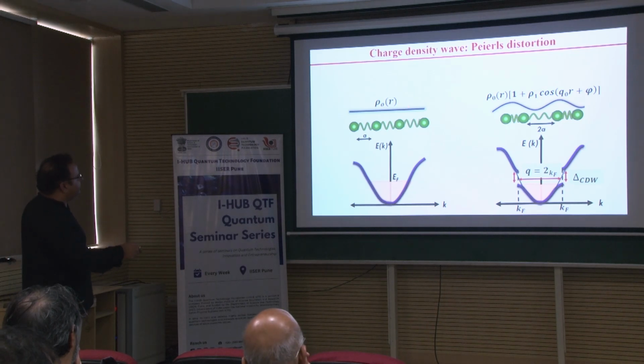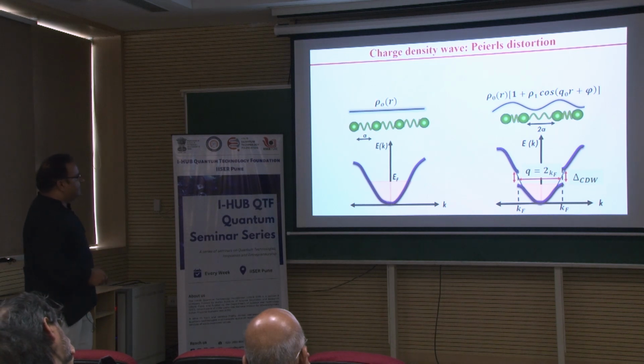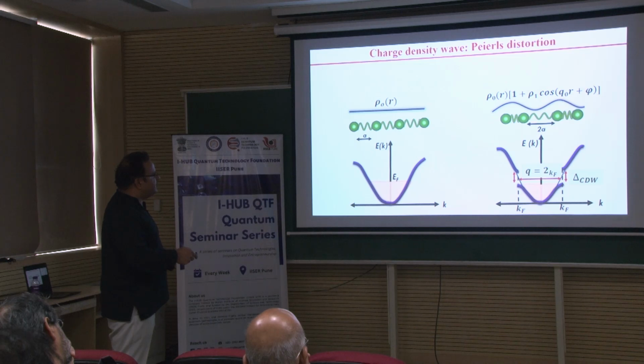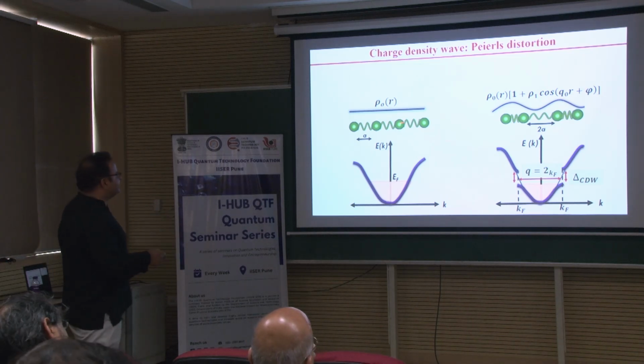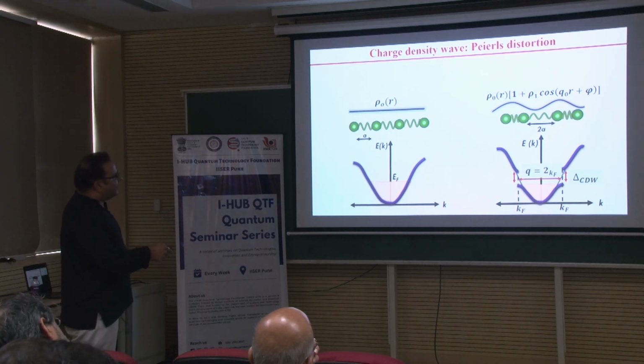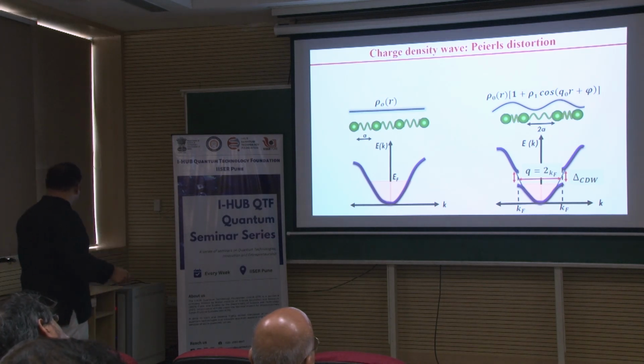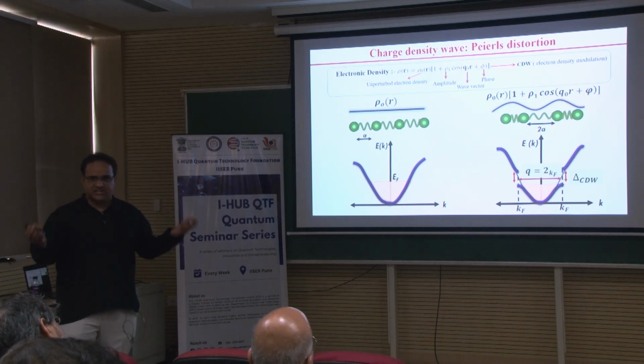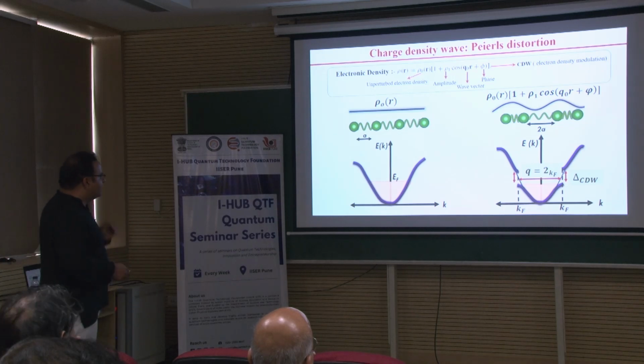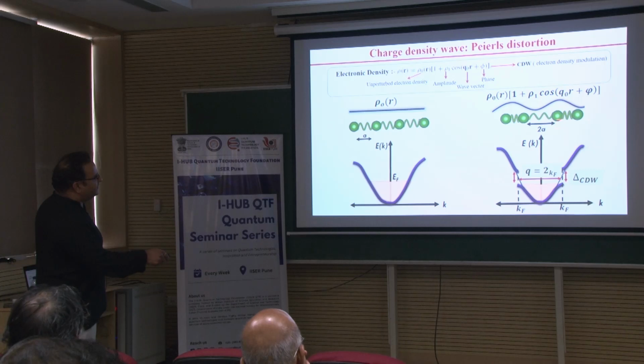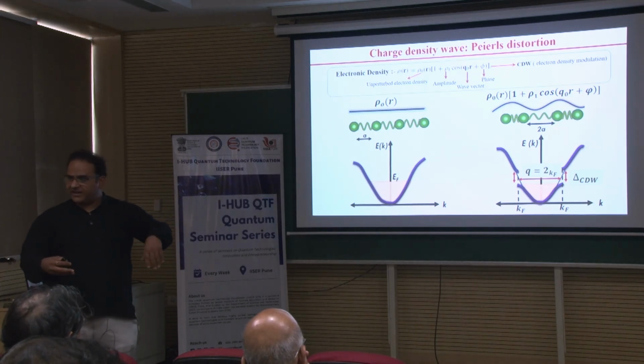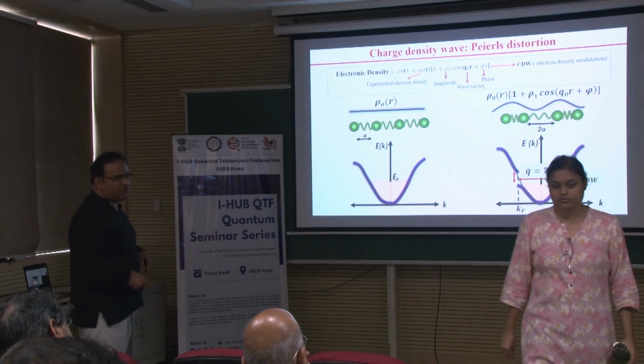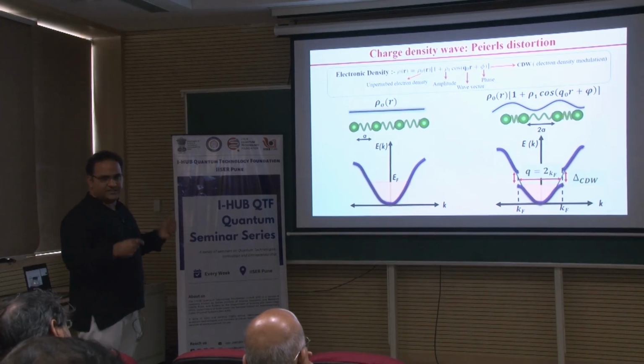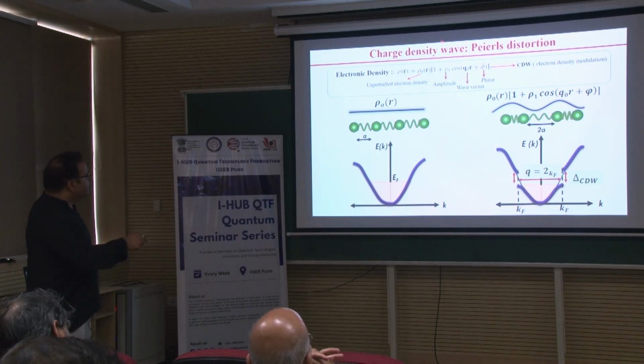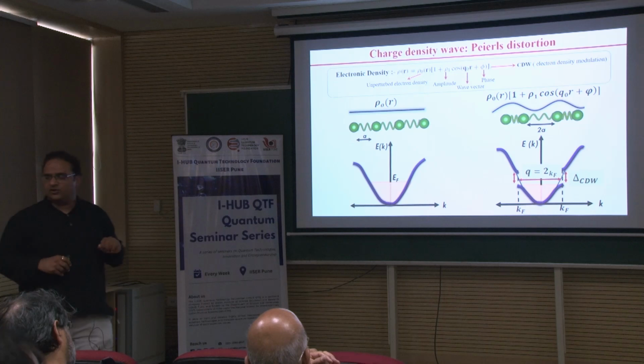This is your Brillouin zone, and now the unperturbed charge density is given by this one. But with the thermal fluctuations, you might see that these atoms, when they are vibrating, may form some superlattice structures which have a periodicity other than this one, and the charge density wave is given by this particular formula. So, you have a modulation of the electronic charge, and you have a modulation of the lattice as well. So, now let us consider that this is A, and now this is 2A. When you look at the reciprocal lattice space, it is 1 by A and 1 by 2A. So, your Brillouin zone is half here. So, you have a folded Brillouin zone, and you have a gap which is coming up because of the periodicity here, and that gap is the charge density wave gap. Your charge density wave is given by the amplitude here, and you have the wave vector and the phase, and they all give rise to how the modulation will look for the charge density.